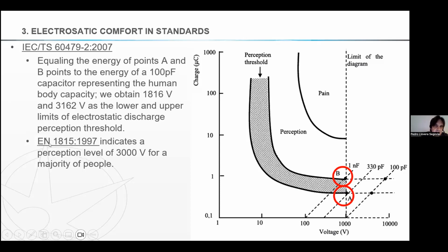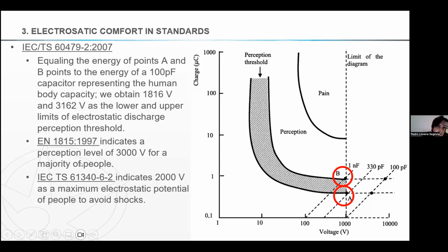Some standards like EN 1815 say that it's around 3,000 volts for the perception level of the majority of people. This new technical specification indicates 2,000 volts, something in the middle. So of course you cannot give an exact voltage level for perception, but it's around this level. Let's say we can more or less say that 1,000 volts is not a problem from an electrostatic comfort point of view, but it's a problem for many other things. For ATEX zones, for electronic handling, so we don't need to limit electrostatic potential so strongly.